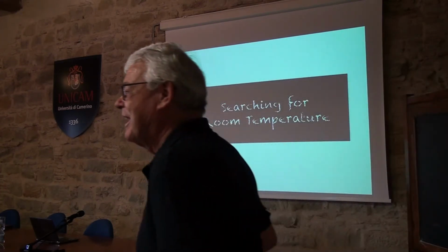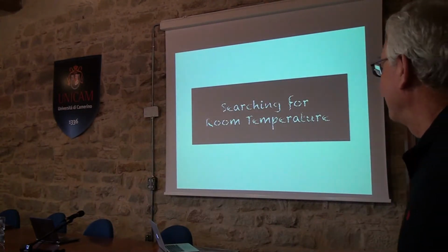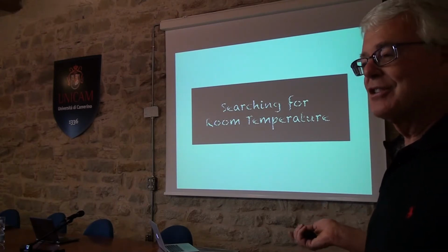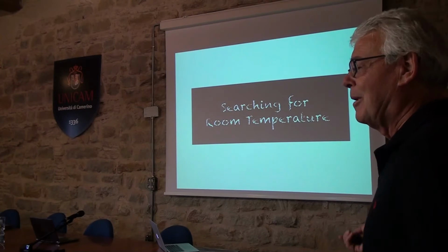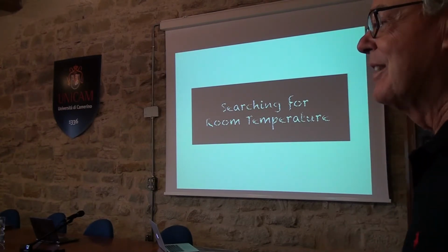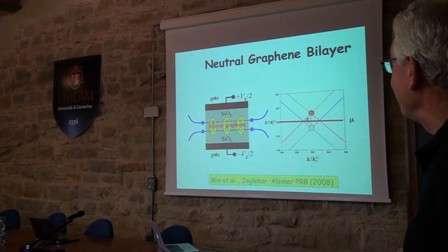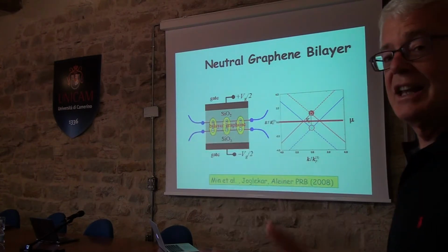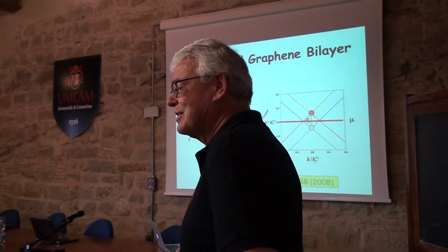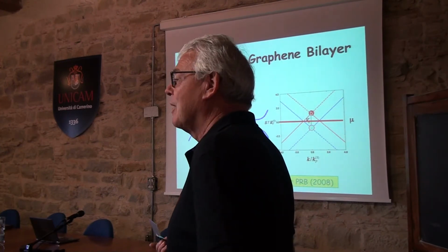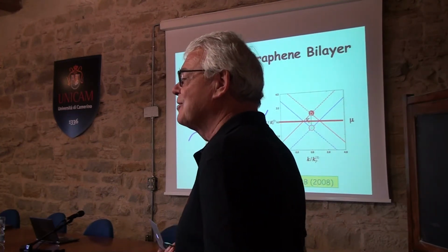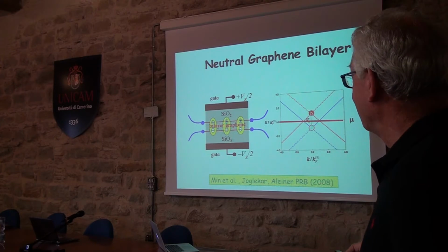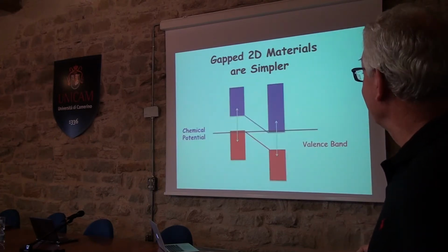Be nice if we had this at room temperature. In the quantum Hall bilayer exciton condensates, this stuff doesn't occur above 100 millikelvin, or below 5 Tesla magnetic field, so it's not very useful. Graphene is attractive in many ways, as Alex was explaining. I think that Leonid's experiments pretty convincingly show that the electron-electron interactions in graphene are not strong enough for this effect to occur. And so maybe bilayer graphene will get you there.